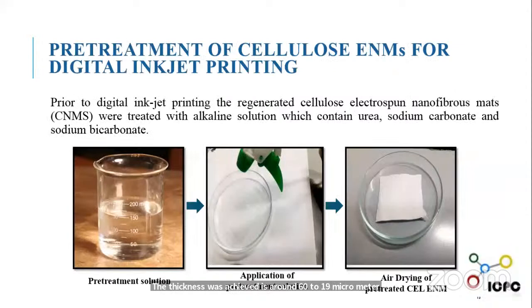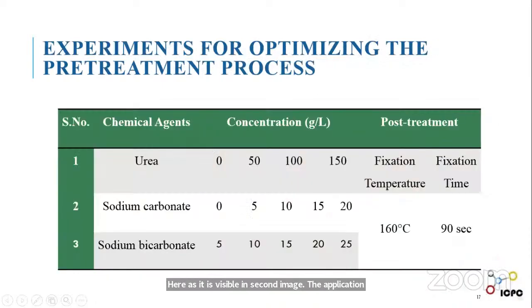Prior to digital inkjet printing, the regenerated cellulose electrospun nanofibrous mats were treated with an alkaline solution which contained urea, sodium carbonate, and sodium bicarbonate, as alkali is required for ionization between the hydroxyl group of cellulose and the reactive group of reactive inks. So we pre-treat the samples prior to digital inkjet printing. The pre-treatment solution was applied by spray technique onto the sample, as visible in the second image, then air dried, and then we move to the digital printing.